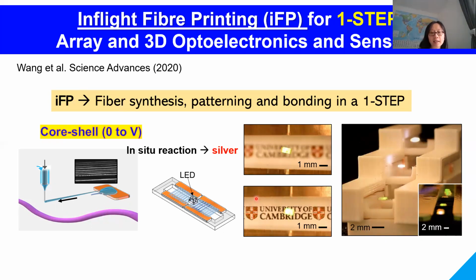Using this technique, we show the printing of silver fibers, and we can form a layered 3D optoelectronic architecture, as shown here. Because we don't use any substrates and it's purely suspended silver fibers, it's highly transparent without any reflections that normally occur with a substrate supported transparent conducting structure.